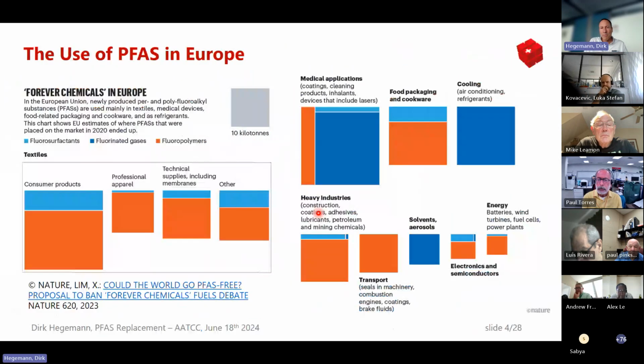One major industry responsible for the accumulation of PFAS in the environment is indeed the textile industry. If you compare the amount, these are data for Europe, to other fields, it's quite substantial, the amount of PFAS that are used, and a lot of them as fluorosurfactants, so that means textile finishings, and exactly this is what's causing the issues, because it's worn, it's abraded, and it's introduced into water after laundering and so on.